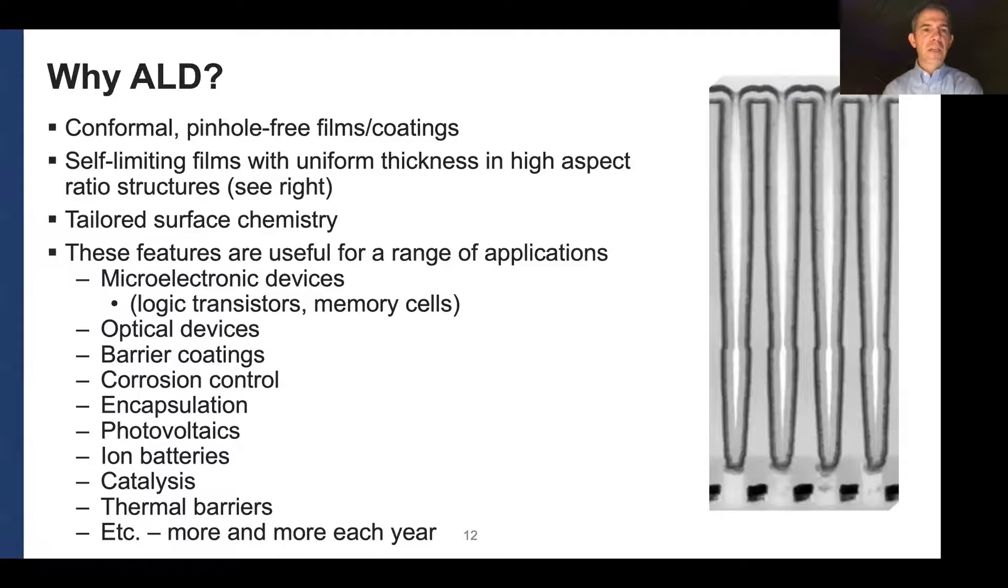So again, ALD, because it's controlled by self-limiting saturating surface chemistry, it allows you to grow conformal films over complicated geometries that are pinhole free. If your surface, your initial surface chemistry is uniform, then you'll have a pinhole free film. If you have contamination or some change in your surface chemistry, that might not be coated by your incoming film. And that's a, an active area of research called area selective deposition, which is sort of intentionally defeating the pinhole free nature of ALD for certain chemistries. But it's been used for lots of different applications. This is a cross-section of some DRAM cells just showing that the films that get deposited uniformly within these high aspect ratio vias in memory cells. You know, and, and you can see, you've got metals and dielectrics and other materials that get deposited in these structures where you, you really need for a well-defined capacitor to have these films be uniform within these structures.